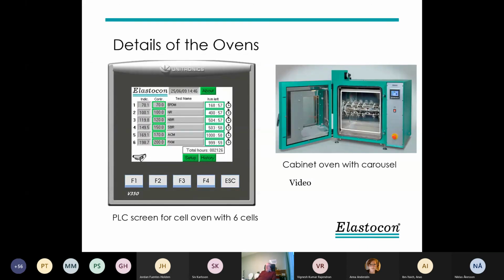There are some details. You can see the PLC we're now using. You can set the name for each test cell, and you set the temperature, and you can set the timer when it should stop, or you can see how long it has been running. That's quite an improvement. So we avoid all these small yellow labels people put on their ovens when they expect to take the sample out. Now you can put that in the program in the PLC instead. Then we have the oven with a carousel to the right there.